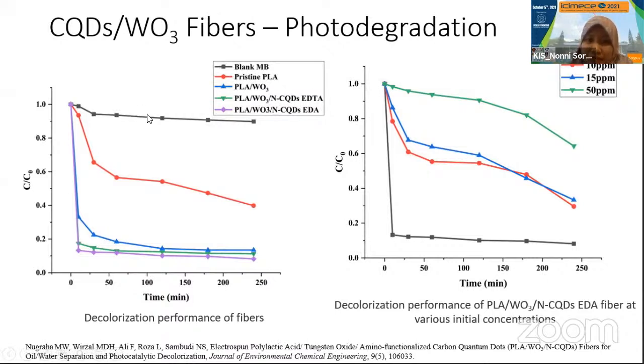Okay. So we also test the same performance by using other concentrations of the methylene blue. So we increase until 50 ppm. For the 50 ppm, we can reach less than 40% of the decolorization, right, after 4.5 hours. So if we want to fully degrade this 50 ppm, then we need longer time for the photocatalytic degradation to happen. But it is expected because we have a higher number of pollutants at this 50 ppm. Okay, so the performance of the 5 ppm is quite good, while for the 10 and 15 ppm, we find that the performance is quite moderate, while the performance of the 50 ppm is quite low.